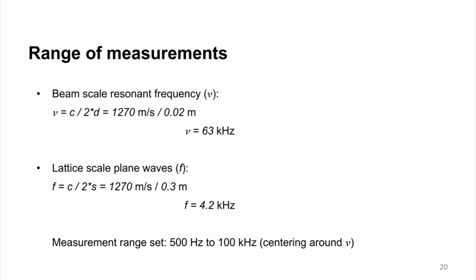So for what range should I be measuring the frequencies present in metamaterials? For that, I decided to do resonance calculations for individual beams in the metamaterial, as well as on the scale of the bulk of the metamaterial. For individual beams, I found that a resonance frequency would occur around 63 kilohertz, and for the lattice scale, I find that I would see something like a plane wave around 4.2 kilohertz.